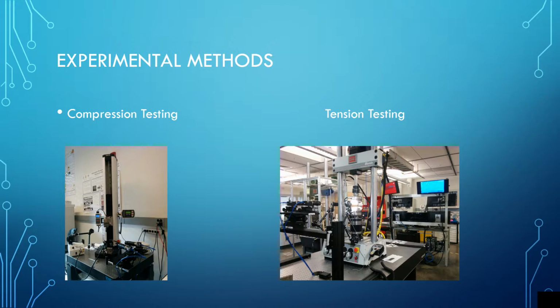In the case of tension testing, a servo-hydraulic testing equipment was used. The make of the machine was MTS. In this case, we slightly differ from the compression testing. A load cell of 25,000 newton capacity was used. It had a larger resolution as compared to the compression testing. The load cell in this case had a resolution of 5 newtons.